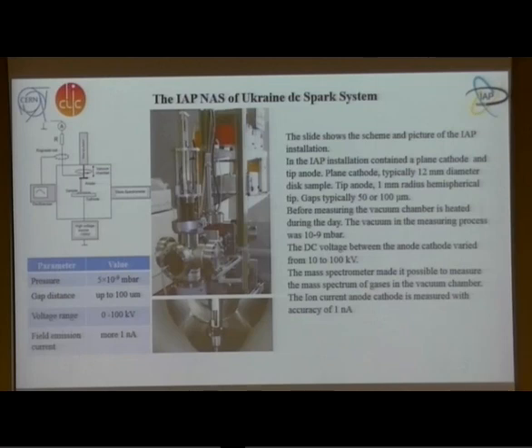Before measuring, the vacuum chamber is heated for one day. The vacuum in the measuring process was 10^-9 millibar. The DC voltage between the anode and cathode varied from 10 to 100 kilovolts. The mass spectrometer made it possible to measure the mass spectrum of gas in the vacuum chamber. The ion current between anode and cathode is measured with an accuracy of 1 nanoampere.